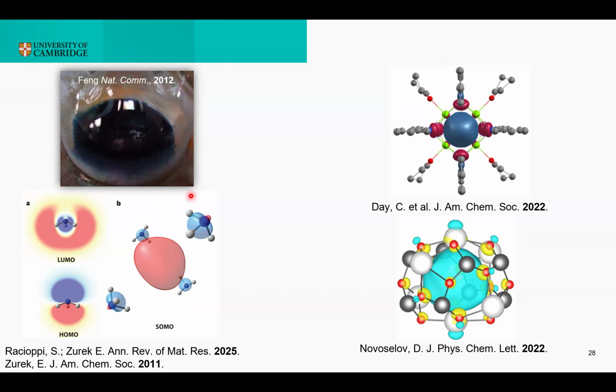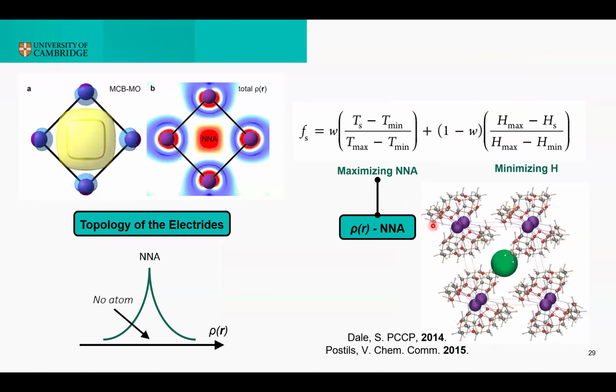But molecular and crystalline electrides can also form through generation of other multi-center bonds, like in this case of this magnesium 4 cluster that was observed experimentally, but also in the case of the activated mayenite. The good news is that basically all of these systems that we classify as electrides have in common a very specific feature of the electron density that is called non-nuclear attractor, or NNA. A non-nuclear attractor is a maximum of the electron density that, however, does not correspond to an atomic position.